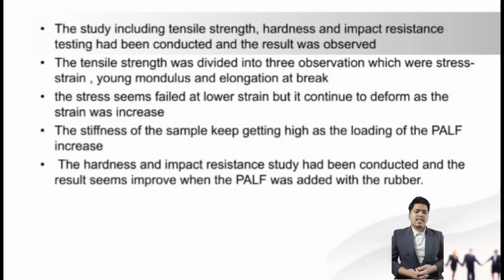The study including tensile strength, hardness and impact resistance testing had been conducted and the result was observed. The tensile strength was divided into three parts, which are stress strain, Young modulus and elongation at break. The stress seemed to fail at lower strain, but it continued to deform as the strain was increased. The stiffness of the sample kept getting higher as the loading of PALF increased. And also, the hardness and the impact resistance study had been conducted and the results seemed improved when the PALF was added to the rubber.